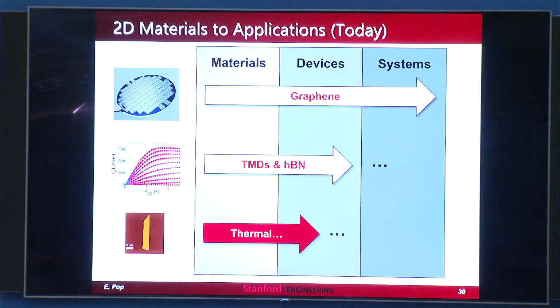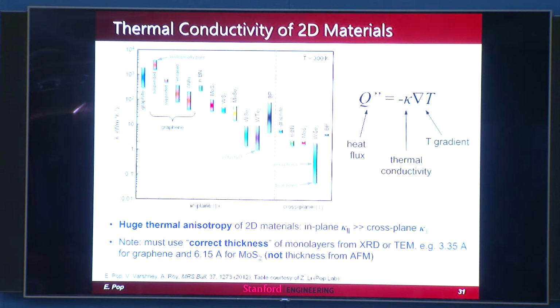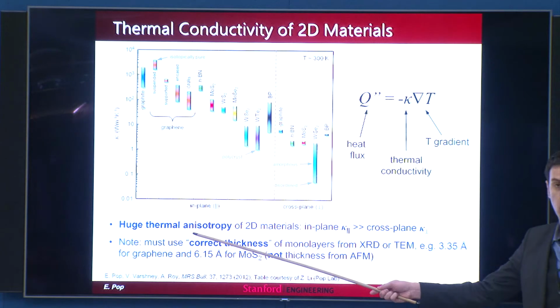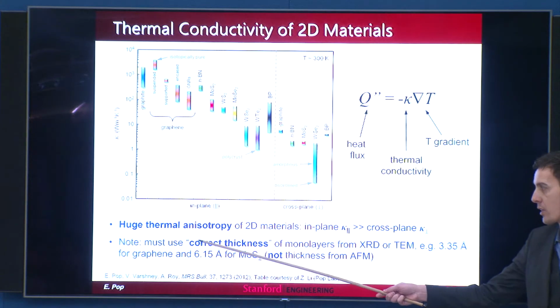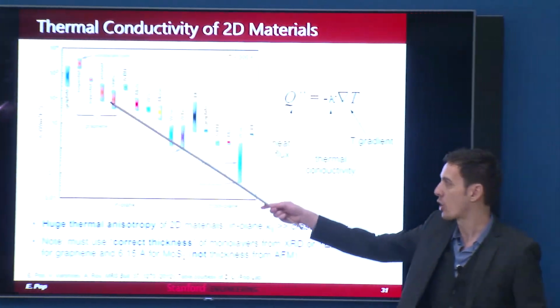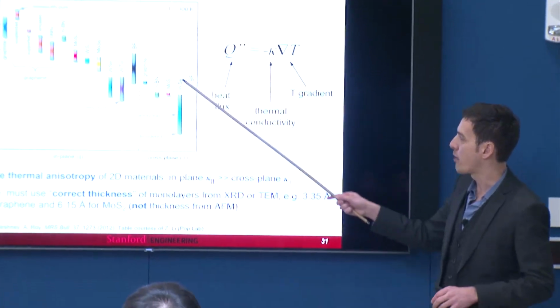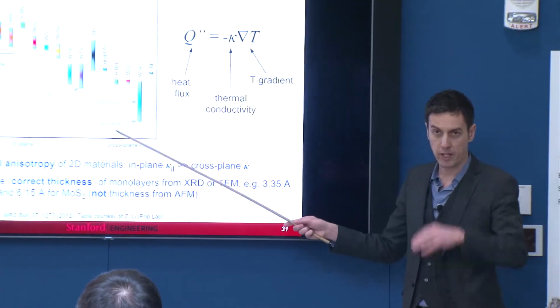So I probably just have a few minutes left. And I just want to say a couple of words, maybe 5 slides, about the thermal measurements that we're doing. Again, the take-home message of the thermal measurements is this thermal anisotropy of 2D materials. You don't really get this in 3D. In 2D, you have very large thermal conductivities in plane, but you have pretty lousy thermal conductivities out of plane, cross-plane, because of the weak van der Waals bonds, right?